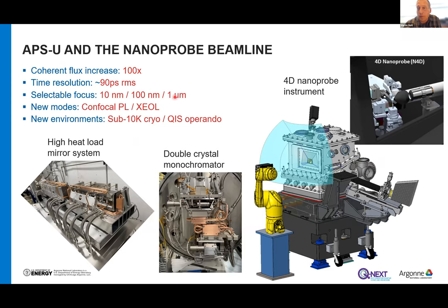So both having a 10 nanometer zone plate and 100 nanometer zone plate on the same scanning platform, and then a 1 micron beam with a CRL lens outside the chamber. That's really important. It's hard to do with hard X-rays, but then you can see nanoscale perturbation in the context of a larger environment or device stack with statistical significance, because that's the part that microscopy is really lacking.